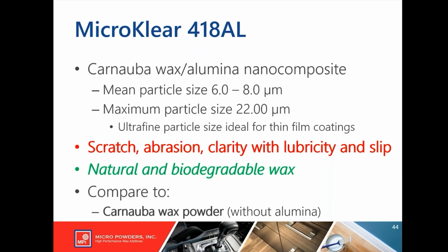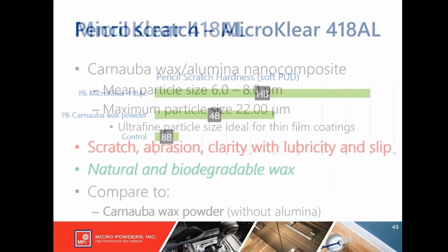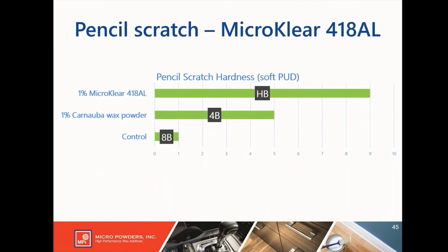And here we're going to compare just the micronized carnauba wax powder. So again, control 8B, 1% of carnauba wax powder improves the pencil scratch hardness to a 4B. Put the aluminum oxide inside that carnauba wax particle, you get MicroKlear 418AL, improves from a 4B to an HB.